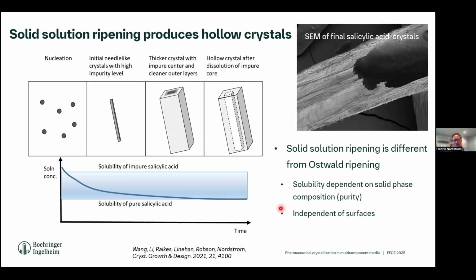as we are having these changes during the crystallization, we're starting at a very high impurity level and slowly reducing it. That also means that we're changing the solubility of the material over time. So you can think of it sort of like a ripening mechanism that happens. In this particular case with salicylic acid, you form these dirty nuclei initially that grow into very thin needles, high aspect ratio initially, and then they start to grow in the more axial direction. So you're getting these impure cores in the beginning, and then cleaner outer edges.